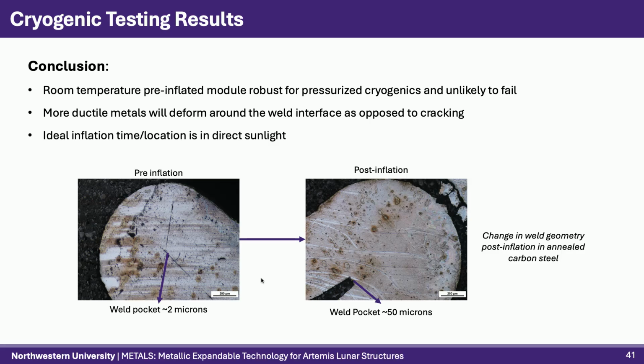Overall, we recommend inflating our inflatables during the lunar day or after warming them up. In our second experiment, we demonstrated that such pre-inflated inflatables are reliably resistant to changes in pressure and unlikely to fail in the cryogenic applications we expect, where the storage pressure is likely not that much higher than the inflation pressure. Also, both experiments demonstrated an undesirable decrease in inflation volume with decreasing inflation temperature, so inflating at warmer temperatures would negate this. And finally, the only inflatable that failed throughout all of our testing was the one inflated at the lowest temperature. Now, if we inflate while it's warm, we negate this.